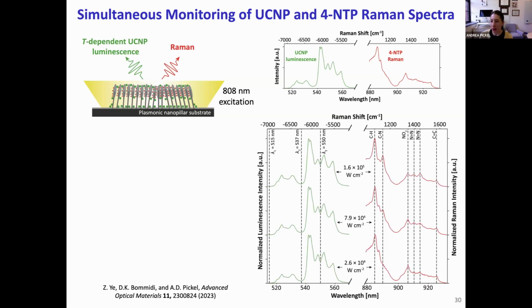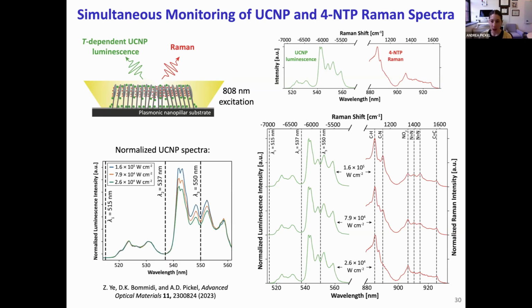We also find that the same range of laser excitation intensities can progressively photocatalyze the 4-NTP dimerization and excite our UCNP thermometers. So as we increase the laser intensity, we see new Raman peaks associated with the DMAB product appear. And we also see that a peak associated with the 4-NTP reactant decreases, both of which indicate that the reaction is occurring. And while it's difficult to see by eye in this format, the green UCNP spectra are also undergoing a change in relative emission intensity as we increase the laser power that indicates a temperature rise, which we can observe more clearly if we plot the same UCNP spectra on a normalized basis.